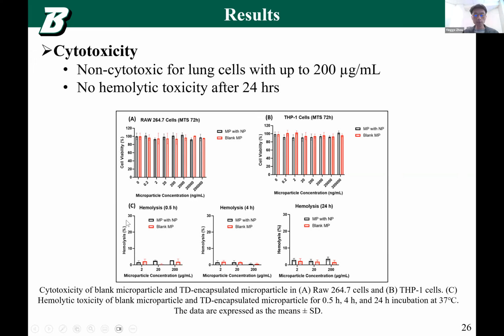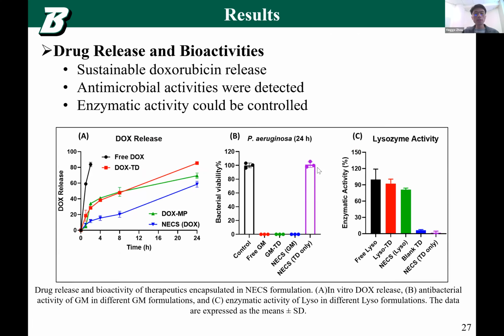They also wanted to test if the microparticle has an effect on hemolysis, which means if the cells will bleed. And the result shows that they both have a minimized hemolysis effect on the cells. And then we test the drug release.